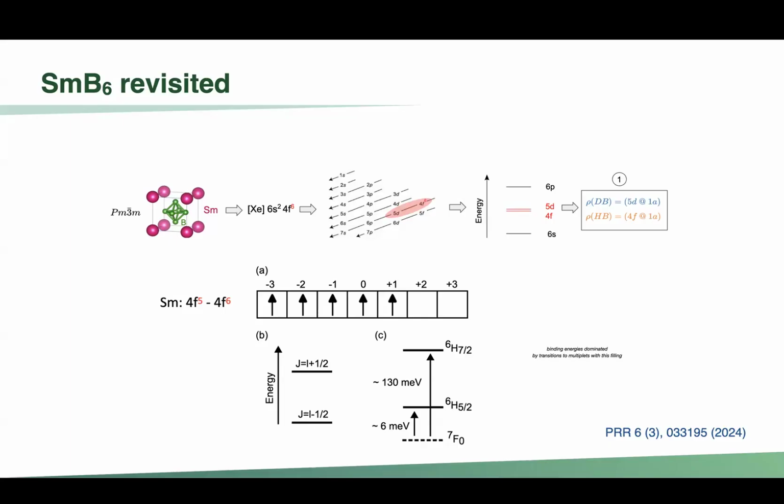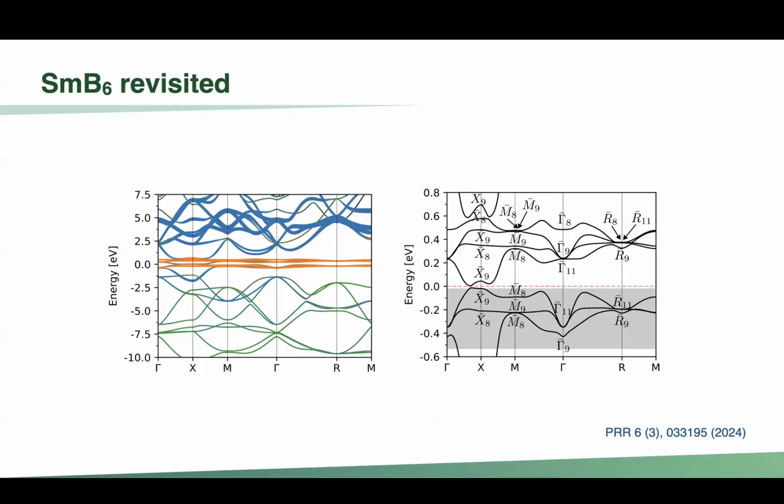And because topology is one of these very robust properties of materials, if the gap has the same symmetry for both the many-body wave function and the Bloch wave function, in principle our machinery should work. So we did DFT calculations with one of these elaborated pseudopotentials, and here we can see the f flat bands, and here we see a d band that is crossing all the f bands, and they are hybridizing, and in this region is where we get many gaps.